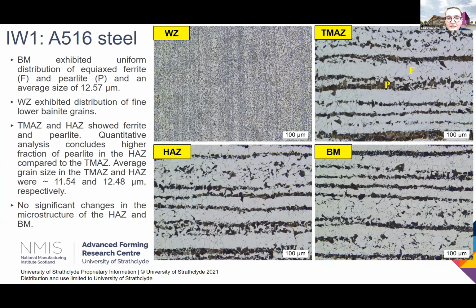Moving on to the ferritic steel, you can see that there is very little difference in the microstructure of the base material, heat affected zone, and thermomechanically affected zone. I think there's very little difference in the grain size. The heat affected zone is about 12.48 micrometers and the thermomechanically affected zone 11.54, so not that much difference. The only difference is really in the weld zone, where we have very fine lower bainite grains that are a result of the temperatures that we experience within the weld zone and also the cooling rates within the weld zone.